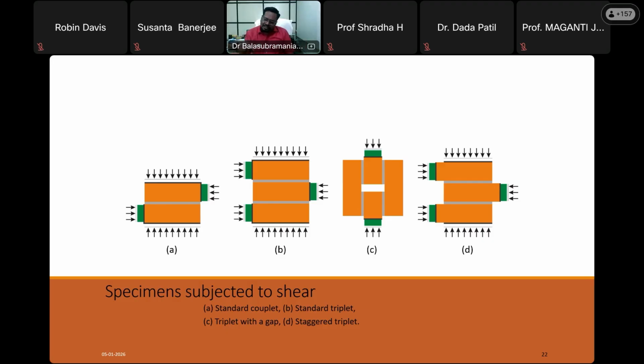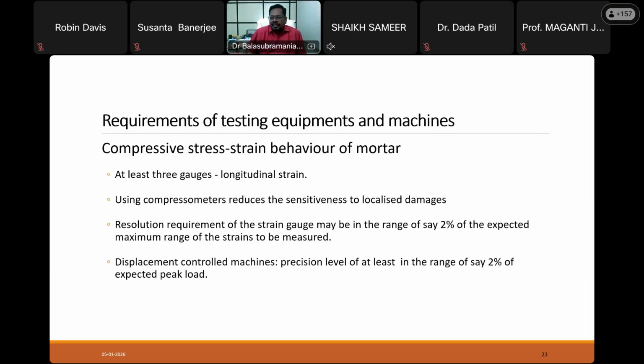Shear bond strength will be nothing but the y-intercept of the Mohr-Coulomb failure envelope, and the coefficient of friction will be nothing but the slope of the Mohr-Coulomb failure envelope. So different levels of pre-compression, say 3 or 4 levels, can be given and the shear capacity obtained in the lateral direction. To get the 2 or 3 levels of pre-compression, we can perform the test and get the shear strength values, and we can construct the failure envelope. Okay, from that we can indirectly get the shear bond strength as well as the coefficient of friction.